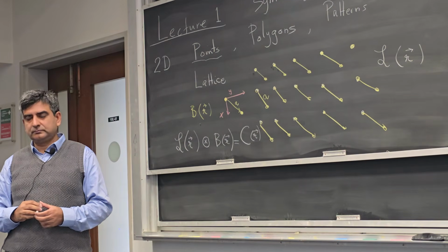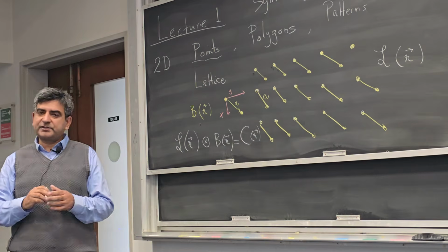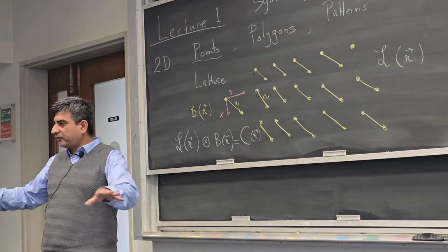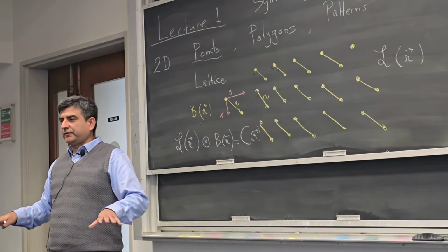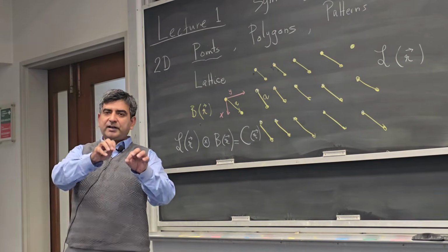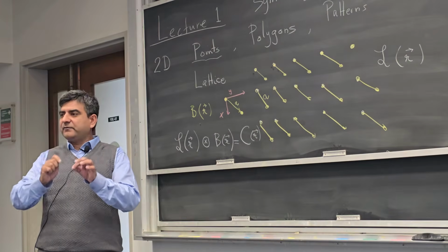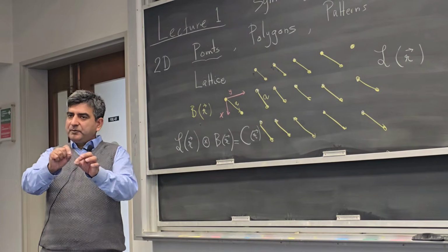Yes. So the lattice is an abstract thing, a place to put our actual atoms, and it's not something physical itself. Right. So the crystal structure is a convolution between the lattice, which is the grid of placeholders for the motifs, and the motifs attached to each lattice point. Each motif has the same functional relationship with the lattice point.